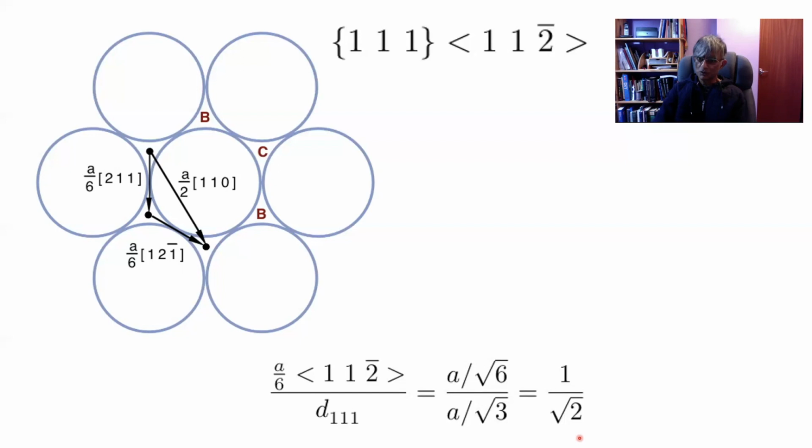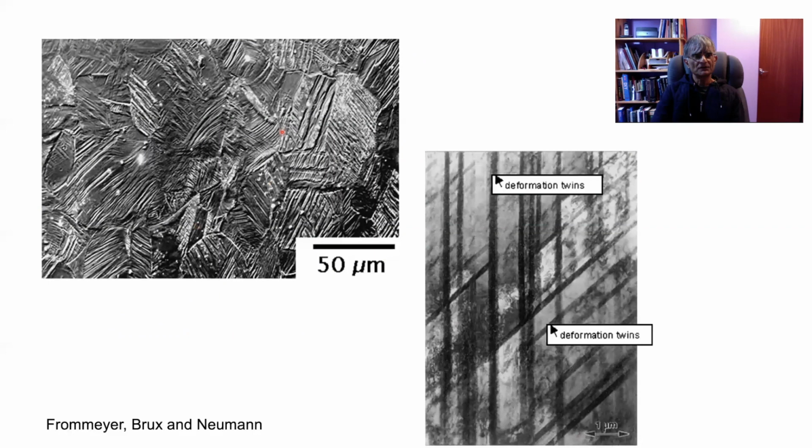So here is the surface relief produced when you take one of these materials, which is fully austenitic. So when we deform it, there is no hope that it will transform into something else. But it deforms by mechanical twinning, and you get these very beautiful, extremely thin, lens-like mechanical twins in the microstructure when you plastically deform. Of course, you also get some dislocation deformation as well, because remember, we are dealing with a polycrystalline system, and that can be messy because the grains have to maintain compatibility between adjacent grains.